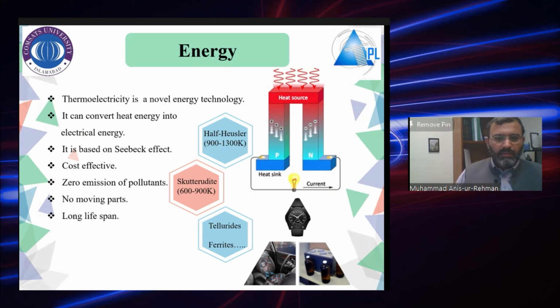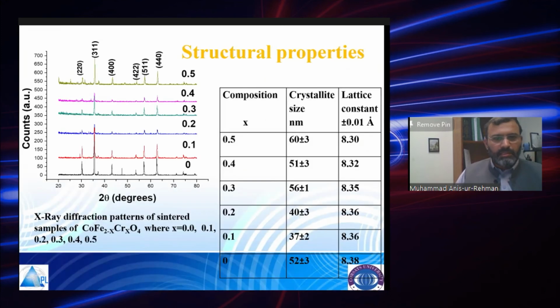Usually half-Heuslers, skutterudites, tellurides or cobaltides are studied for their thermoelectric properties. For ferrites, we can find very rare literature. We have investigated ferrites to be a potential candidate for thermoelectric materials. For this purpose, we have selected cobalt ferrite, and on the iron side we have used chromium.